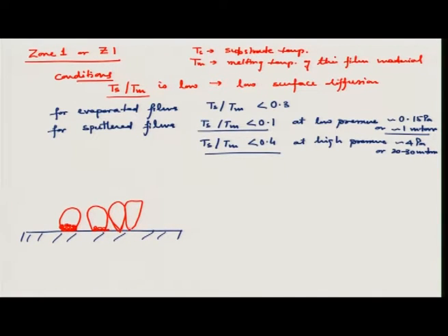Now, recall, as soon as you have a certain layer, and you have a directional input for thermal evaporation or sputtering, the area very next to this growing thin film is not receiving material because of the shadowing effect. Any molecule which is coming will get adsorbed here rather than go where its shadow lies. So it will grow like this.